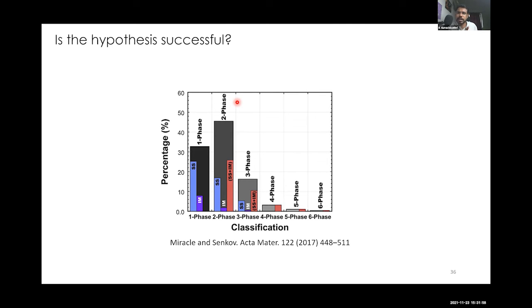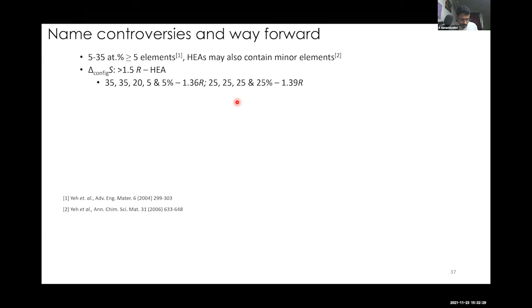But there is something called the Gibbs phase rule in metallurgy that says you can have multiple phases in equilibrium if you have multiple elements, multiple components in your system. Okay, at least that is not working here. So there is something that this configurational entropy does. At least it minimizes the number of phases. Okay, so that is one thing we can see, although our initial intention did not work out. Okay, so there were controversies popping up when people realized that this hypothesis is not working.